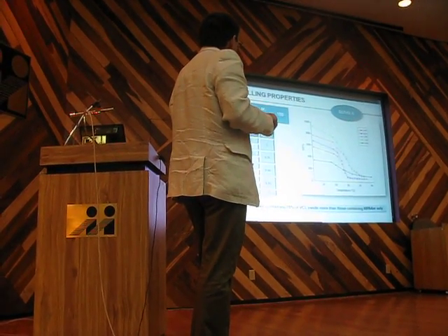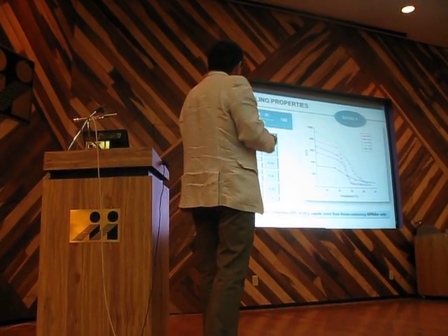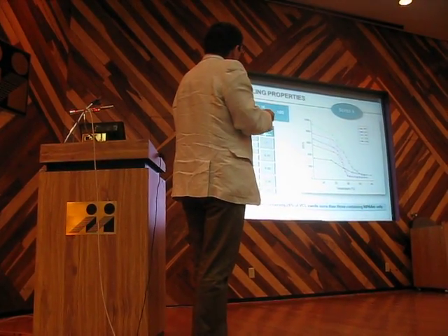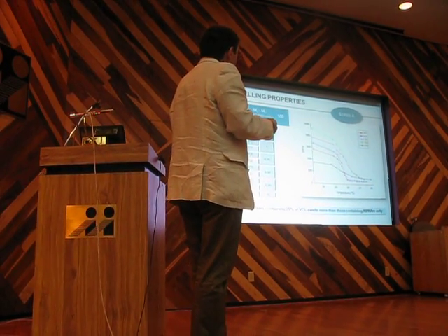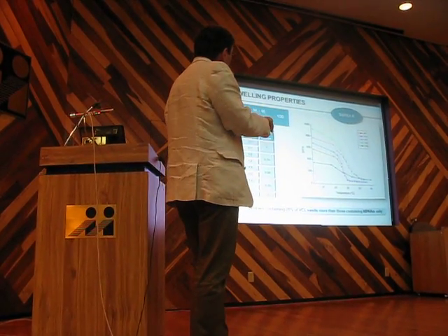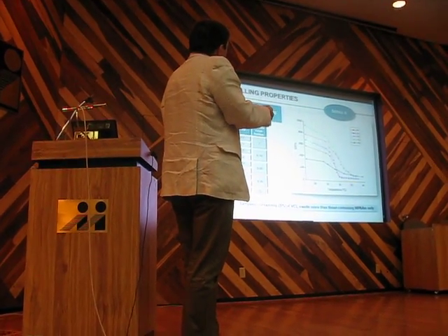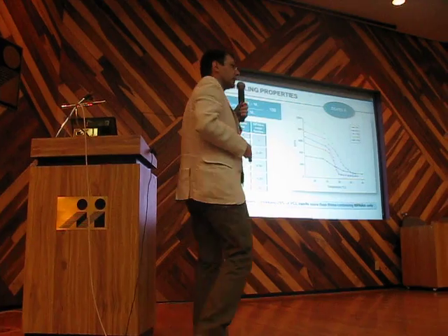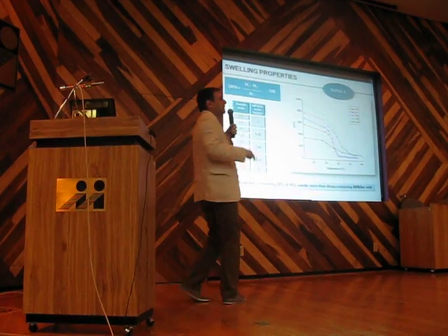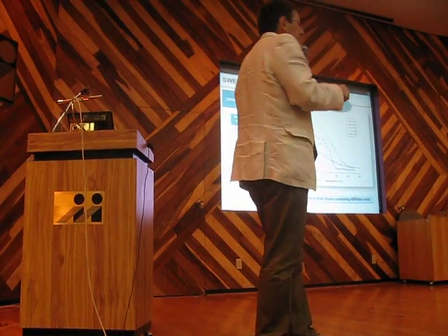What can we see here? The black trend with triangles is this sample, which does not contain NIPAM, and you can see that the transition is not sharp, and also the swelling is not so high. The red and the blue curves are those of the frontally polymerized and classically polymerized samples. Classically polymerized means 80 degrees for 2 hours, 80 degrees of heating.